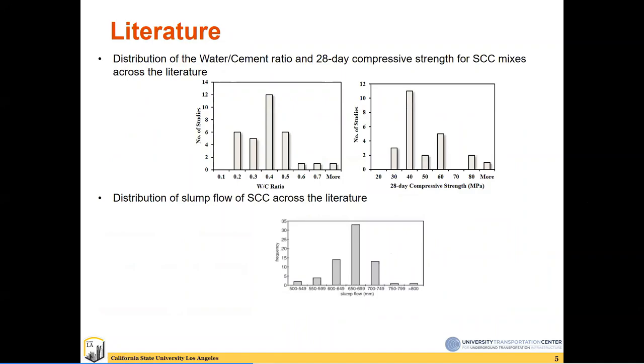A quick overview of the literature about the SCC. Again, the water to cement ratio is a little bit less compared to conventional concrete. For the most part, in the literature it is around 0.4 or 0.5. In terms of 28-day compressive strength, most of the literature studies reported a 28-day compressive strength of 40 megapascal. And there's a significant increase in the slump flow and slump spread of the SCC compared to the conventional vibratory concrete.